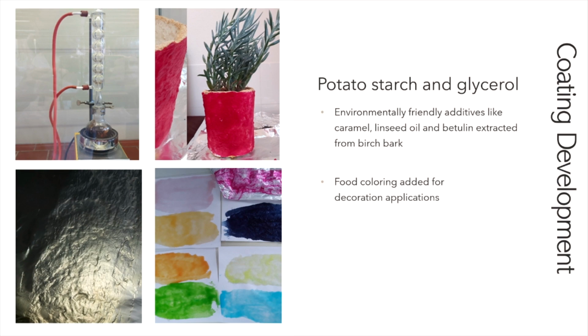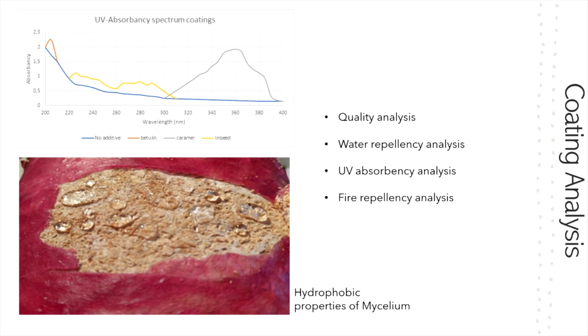The coating was chosen for the fact that it was a cheap and accessible option. The client, McAllen, does not have the ability to use expensive methods and machinery, so it was the perfect option for the company. The additives chosen to do research on were betulin, extracted from birch bark, caramel and linseed oil. The additives were added to the coating and researched. Unfortunately, the additives did not seem to have any big effect on the properties of the coating to protect it against UV light, water vapor and fire.